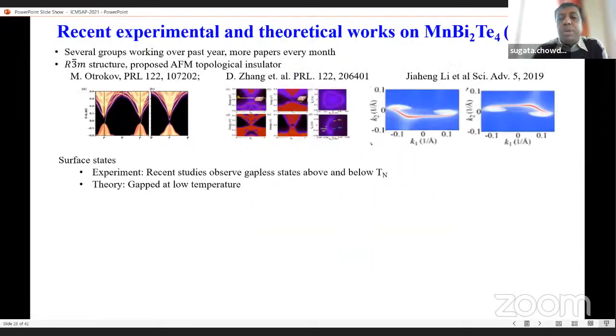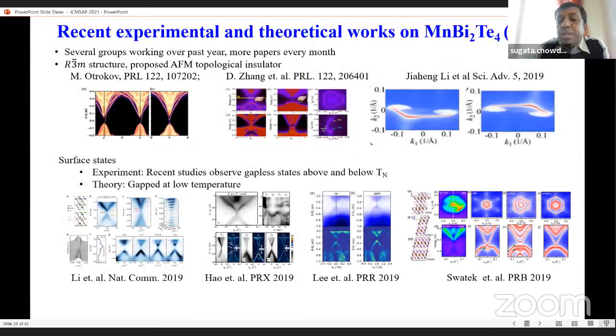So what is the recent work? Different groups have developed different methods. This is the group Otrokov, who first predicted the possibility that the MBT system could be a candidate for the quantum anomalous Hall effect, and at the same time a different group also predicted it theoretically, and then another group experimentally showed that it could be synthesized, and they also observed different features using the ARPES data.